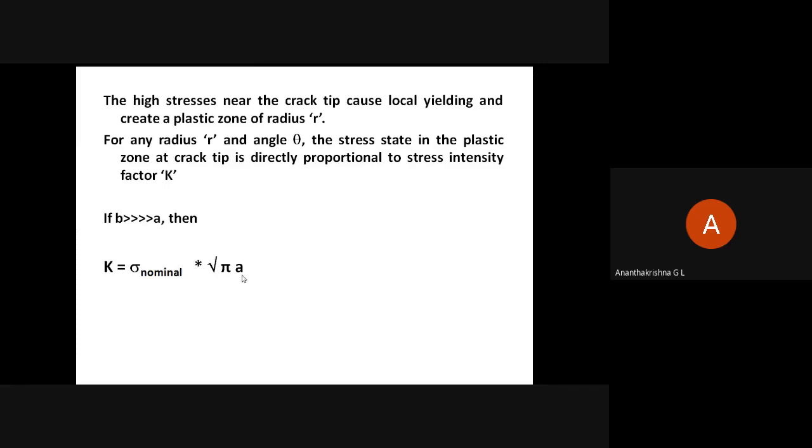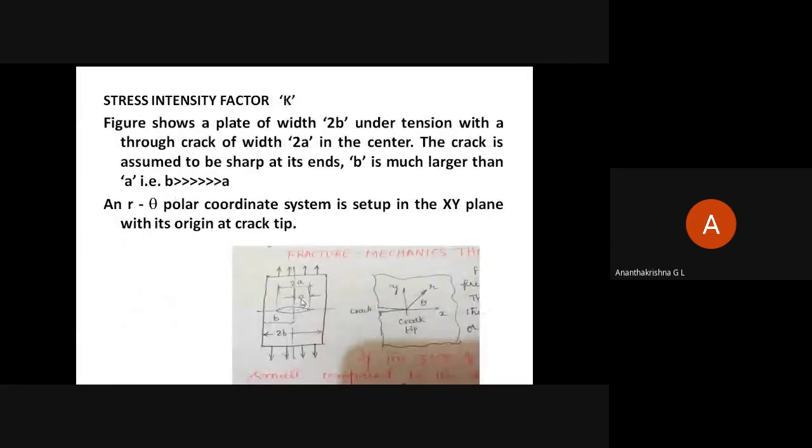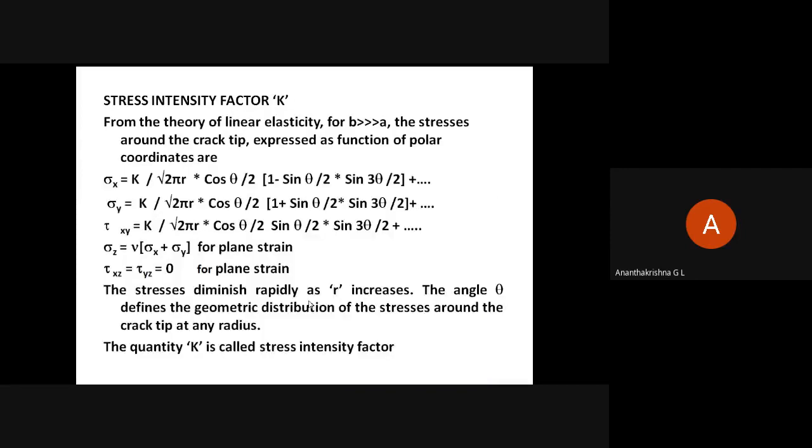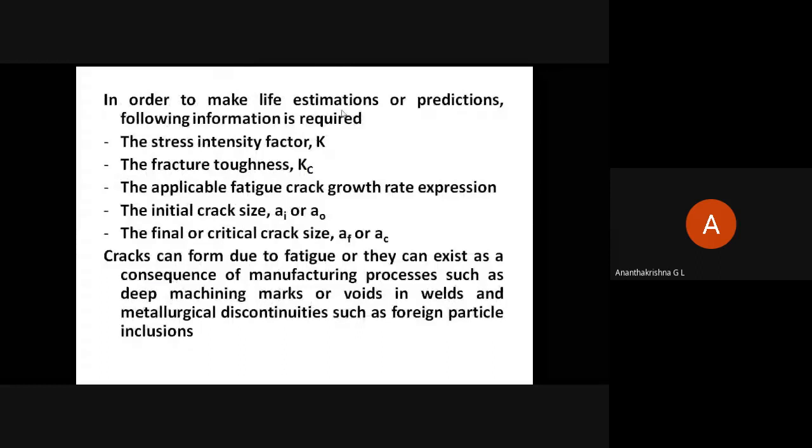a. What does this a stand for? Crack length. Yeah, right. So to estimate or predict the life using fracture mechanics theory, which presumes the presence of crack already, we need stress intensity factor, essentially given by sigma nominal into root of pi into a.